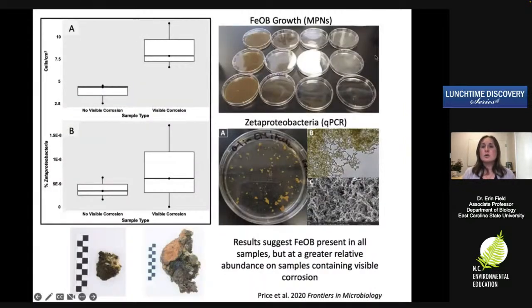So what did we find? So if we look at our MPN results, so again, this is the serial dilution I was showing you. After 21 days, we look for growth. Growth looks like this. That's where you see those bright orange flocks I was telling you about. They're really apparent. And so we know, yep, they're growing, so we can count them. And what we saw is we had iron oxidizers across all the samples. So it turns out they're actually everywhere on the wreck. So that was a little surprising to us, but hey, it's a steel-hulled wreck, so why wouldn't they be potentially everywhere? But we did say they were in higher abundance where we saw visible corrosion, where we saw that rust or their waste product. So we did see higher abundances there.